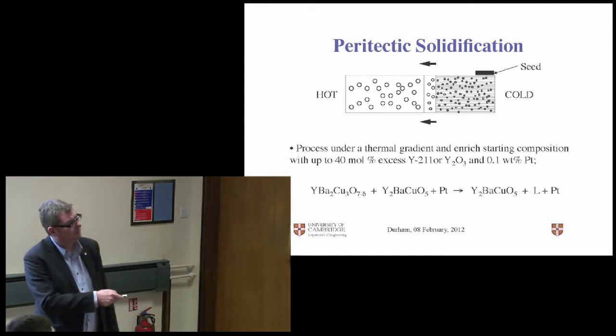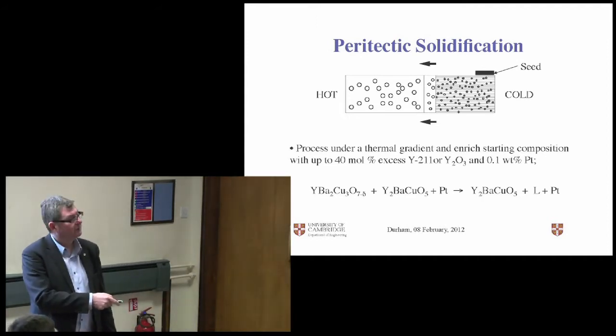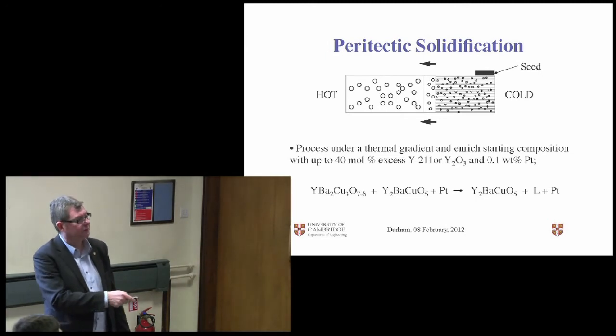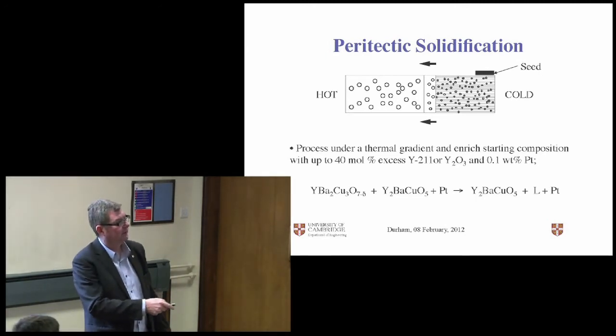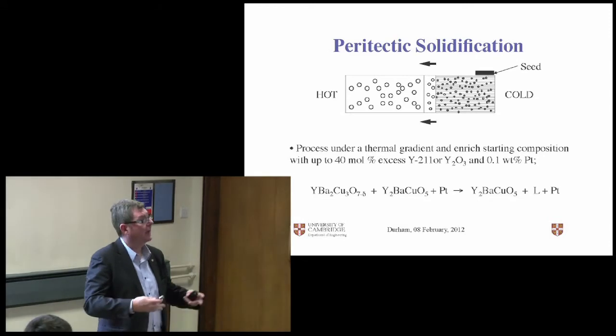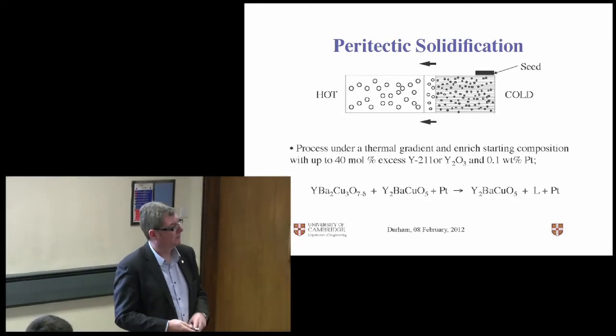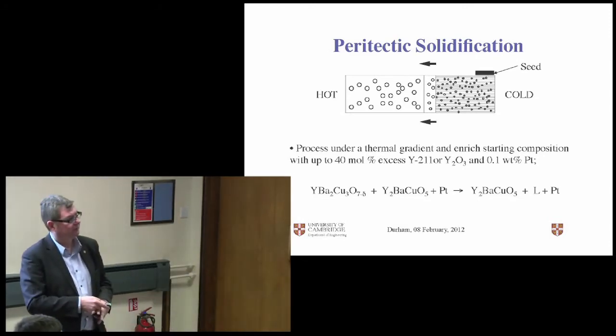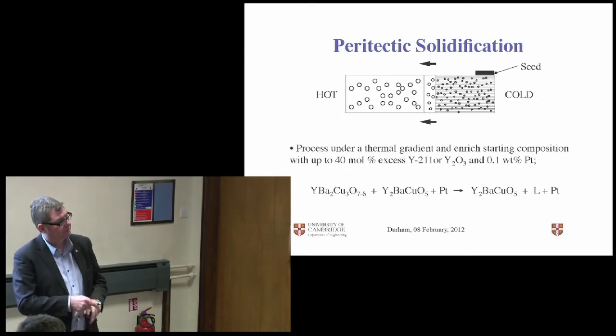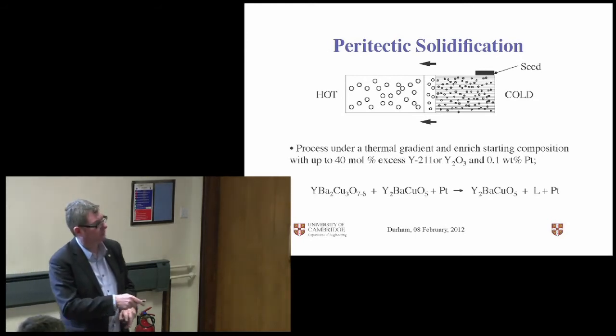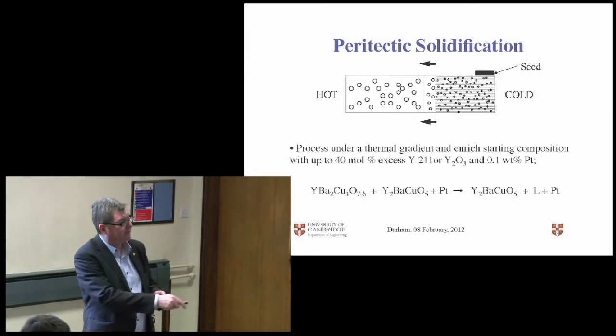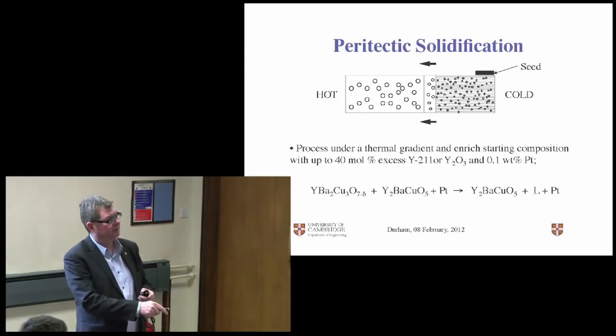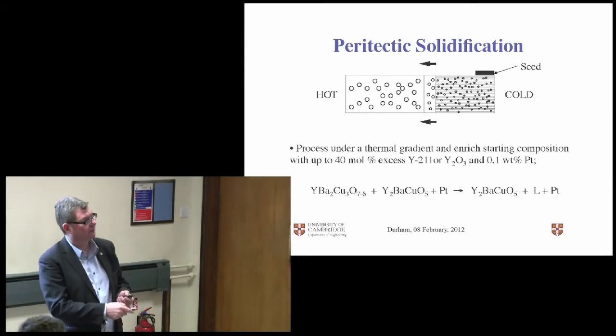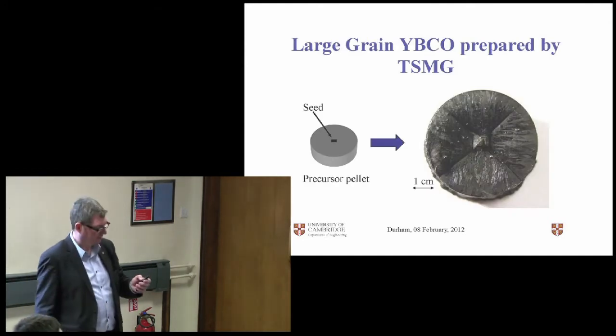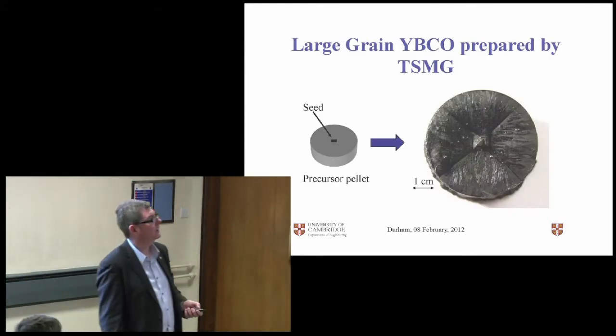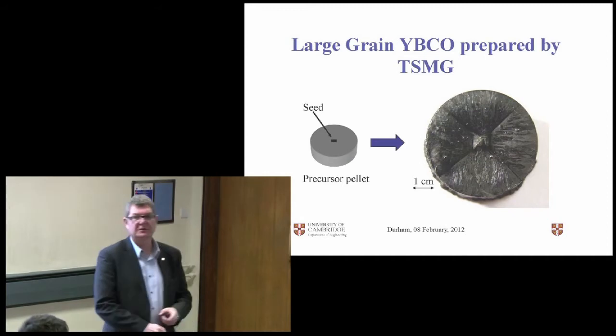But if you actually enrich your starting composition with some of the solid phase that you're producing peritectically, then you've got more solid there to grow, and you've got more solid to keep your liquid in one place. We add a bit of platinum for other reasons, so we enrich our starting composition with up to 40 molar % excess of this solid phase. You can use yttria and you can use other things as well, but basically this gives you fairly good results. And if you get it right, this is the kind of sample you produce.